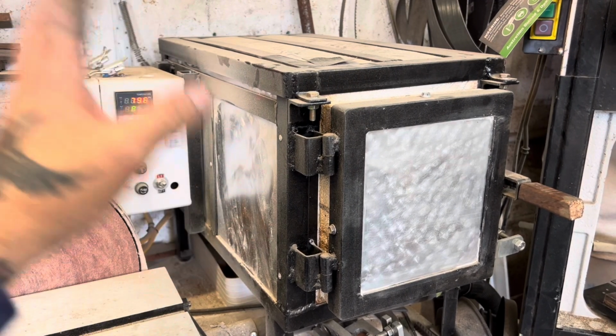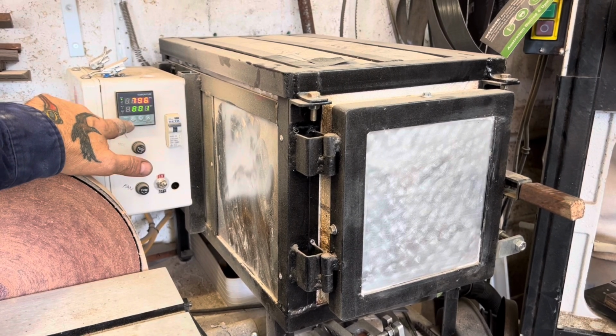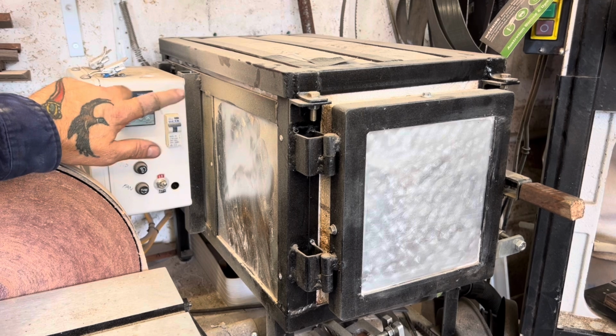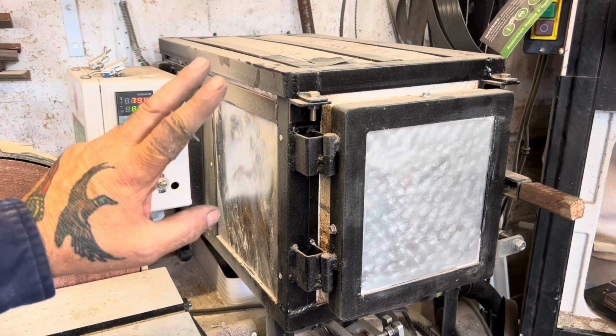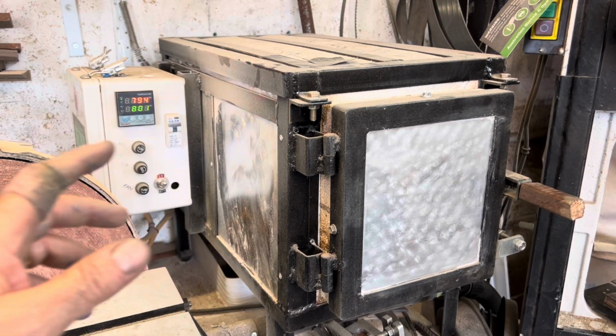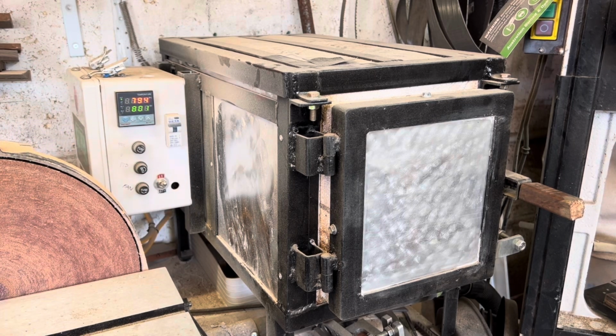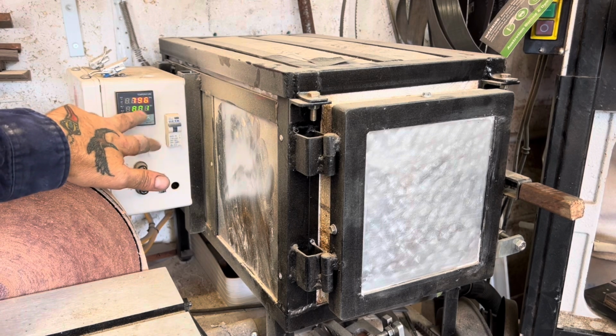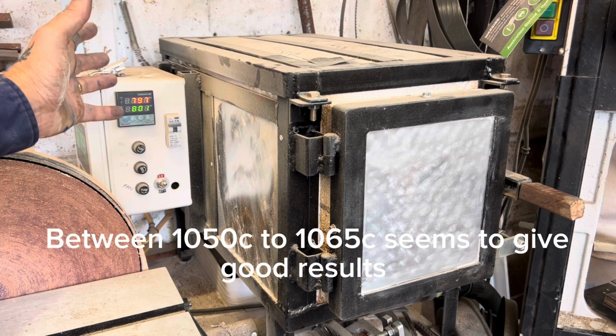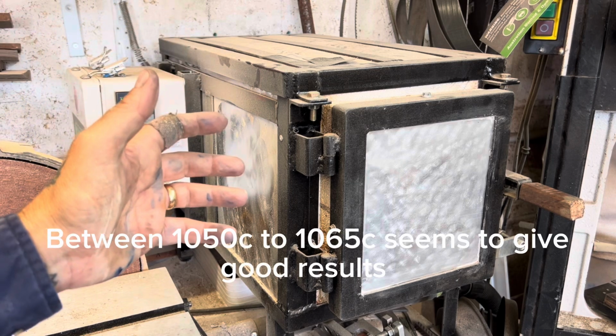As you can see, we've got the kiln fired up, and I've got it set at 801 degrees C there. Now I've got two O1 tool steel blades to do first, so I'll heat treat those first and get them quenched and into the tempering oven, and then I shall raise the temp up on there and get it up to the 1065 for the AEBL stainless steel blades.